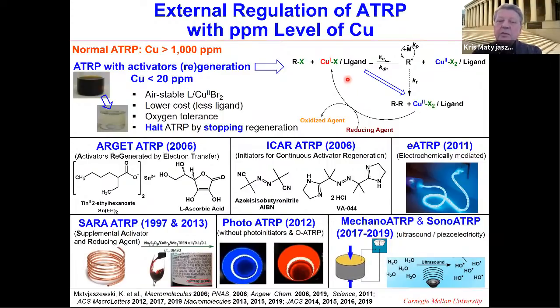There are many advantages of this low ppm copper system because copper 2 is oxidatively stable and we can tolerate oxygen in some sense. And one interesting feature is that, in fact, if you stop regenerating this process, you can stop the entire ATRP. So no Trommsdorff effect or runaway reactions.